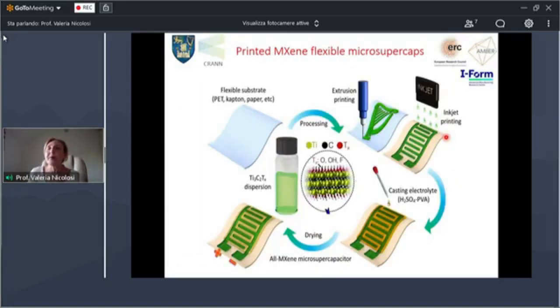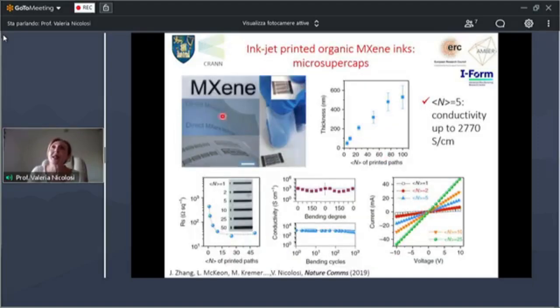Because we can process these materials in inks, and these are inks without additives, without any stabilizer. They are just as made as I showed you before. You can easily print them. So we have developed methodologies to do extrusion printing or inkjet printing of devices, and it really works quite nicely. You can print devices.